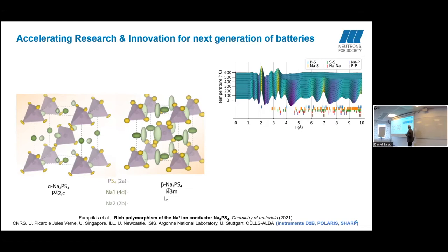And furthermore, going from alpha to beta, the distances between those tetrahedra and the sodium atoms didn't really change at all either. And so from this, they believe that the beta phase isn't really cubic. It has an average cubic structure. But what's really happening is that there's a dynamic disorder, a real time dynamic disorder, and also a spatial statistical disorder of the tetrahedral units that produces, on average, a cubic structure.